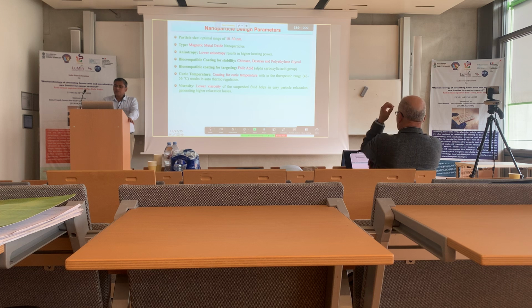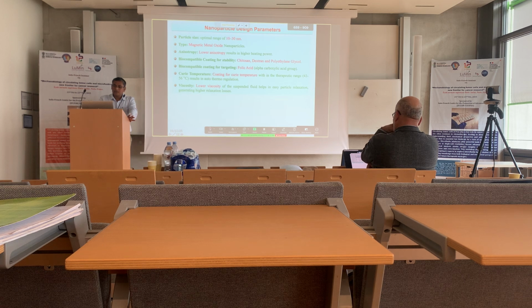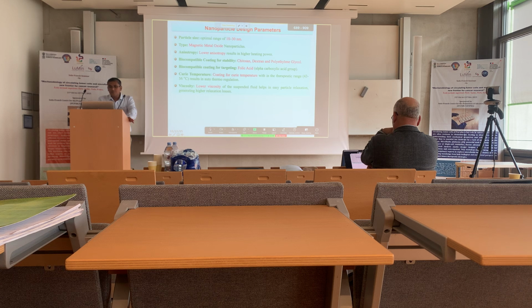Of course, the nanoparticle and its coating, shape and concentration play a crucial role in this kind of therapy. From different reports, we have summarized some recommendations. The particle size should be in the range of 10 to 30 nanometer. Magnetic metal oxide nanoparticles are good for the therapy. Lower anisotropy is good for higher heating power generation, and biocompatible coating for stability and targeting, for the long-term effect, is also an important thing. And one more important thing is that after the test,